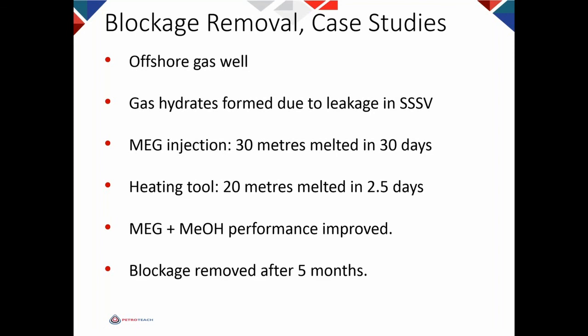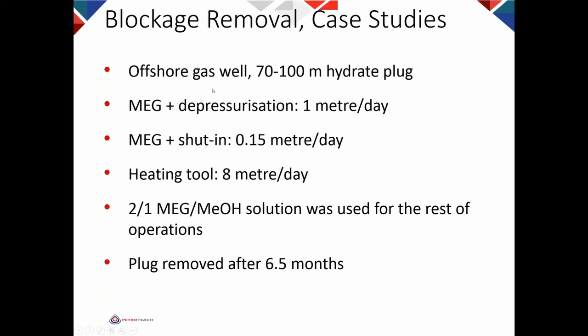Obviously, this experience I'm showing you belonged to more than 20 years ago. Now we understand better. We don't need five months, but it shows that it can take time. Another one, offshore gas wells, 70 to 100 meter hydrate block, MEG and depressurization, 1 meter per day. MEG and shutting, 15 centimeter per day. Heating tool, 8 meter per day. Combination of MEG and methanol, for the rest of operation, and 6.5 months it took to remove the blockage.